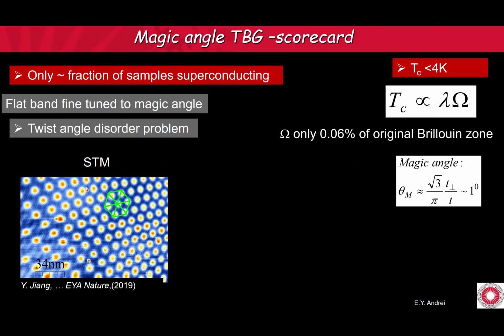So yeah, this is Uemura's formula. But if you take the volume of the flat band in the Brillouin zone, it's only about 0.06% of what it would have been if this was graphite. So you want to increase the twist angle to decrease the period, right? To increase the volume of the flat band in the Brillouin zone. And you see the magic angle is a ratio of the intralayer to interlayer tunneling.